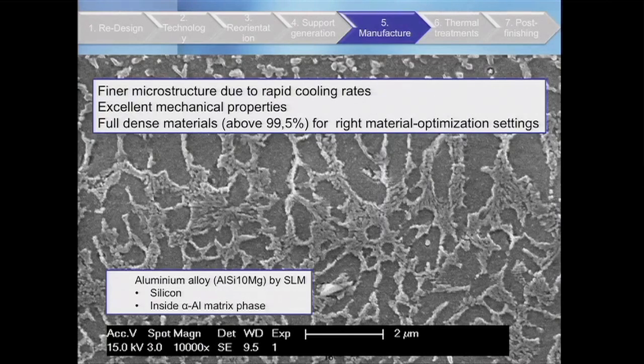About the mechanical properties and the quality of your parts, this is a microstructure of an aluminum alloy. What I can tell you is that the microstructure of additive manufacturing of metals is much more finer due to the rapid cooling that you have. You are melting with a laser so fast and solidifying that you are able to really homogenize your phase distribution and have a very nice microstructure in terms of mechanical properties. You can see there a matrix of aluminum and eutectic with silicon. And if you compare with casting, you will see that it's much more fine. And this will have a reflect in the mechanical properties of your alloy.